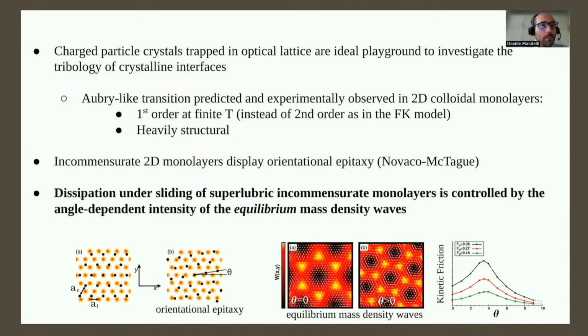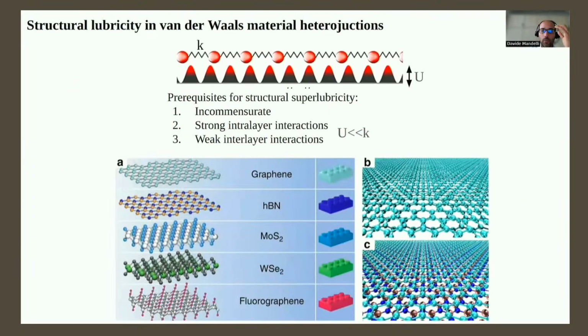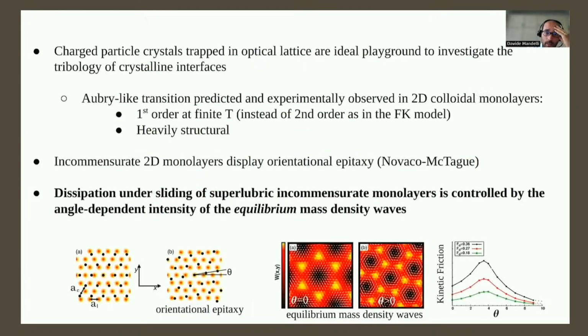So to conclude this part, I would just like to stress these final two aspects: that incommensurate 2D monolayers display orientational epitaxy, and that the kinetic friction is controlled by the angle-dependent intensity of the equilibrium mass density waves. These two are completely general results that are expected to hold also for any other incommensurate interfaces. And just quickly, I would like to show very briefly, in the last minute or so, how the same physics,